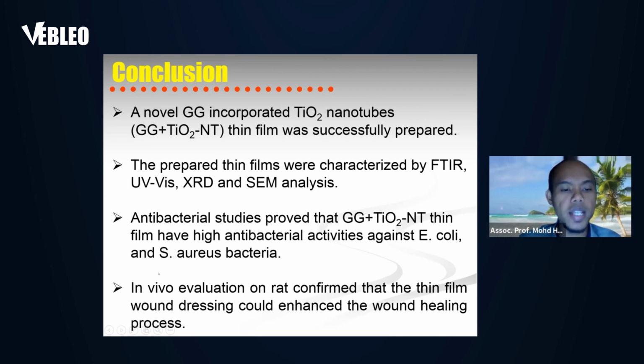Last but not least, in vivo evaluations on rats confirmed that the thin film wound dressing could enhance the wound healing process. As we discussed earlier, the wound on the rats was healed 100% after 40 days, and the scar disappeared. We cannot see any scar of the wound on the rats after 40 days.